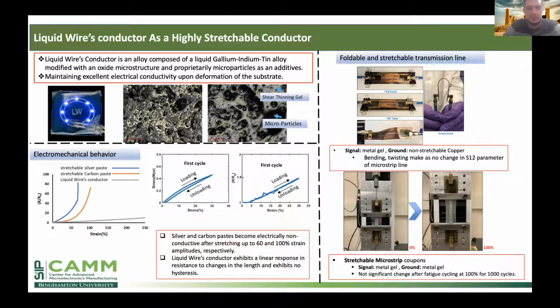This is Banan Garakani. We are in CAMM, part of IEEC in Binghamton, and we're working mostly on flexible and stretchable electronics for wearable applications. In wearable applications, either the person wears it or runs with it, and so the interconnects are typically subjected to large amplitudes of strain. We know that most of these interconnects, even the stretchable ones that are commercially available on the market, cannot survive 10%, 20%, or more than 50%. So we need something that is reliable for tens of thousands of cycles, at let's say 50%, 100%, because it's for wearable applications.